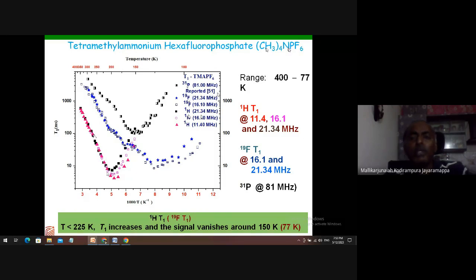Now let us consider this PF6. The tetramethylammonium group with CH3, we call it the cation. PF6 is the anion. In PF6, P is surrounded by 6 fluorine atoms. It also undergoes motions. That PF motion can be measured, and the energy required for it can also be estimated by making this type of measurements. As you can see, for the fluorine nuclei we did it at 21.34 megahertz and 16.10 megahertz, and we got this scattered data. Within all my relaxation measurements, the error bar is well within the dimension of the symbol shown here.